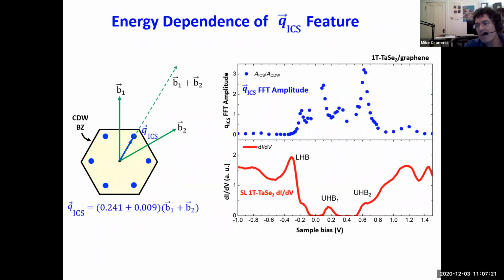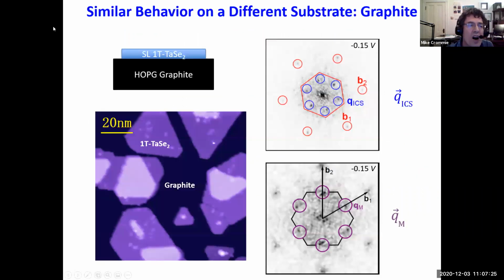So when we saw this behavior, we were really mystified because we'd never seen anything like this before, and we didn't know what it was. And so we wanted to make sure that there wasn't anything funny happening on that particular substrate, the graphene on silicon carbide. So we did the whole experiment all over again on a different substrate. We grew the material on graphite and we did the whole experiment again and we saw the same thing. So that's good. That means that it's not really due to the substrate. Even on two different substrates, we see the same behavior.